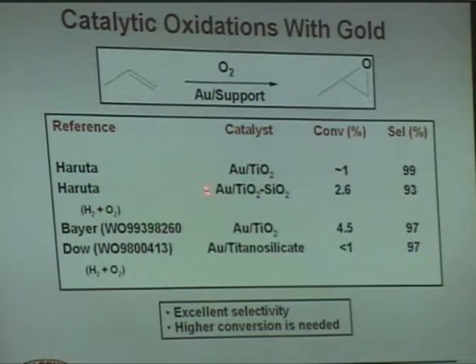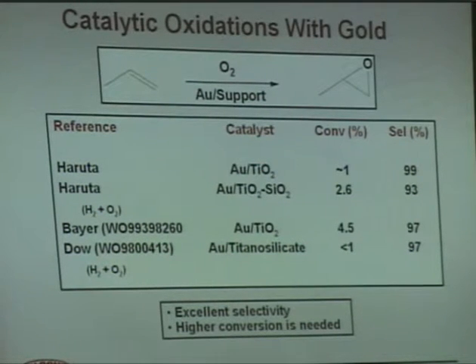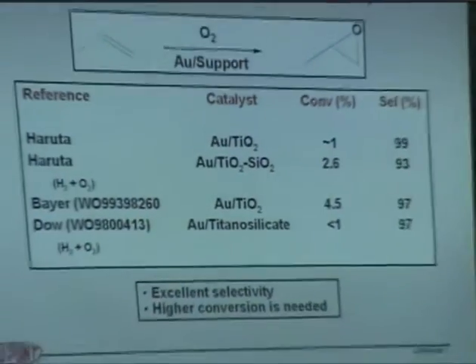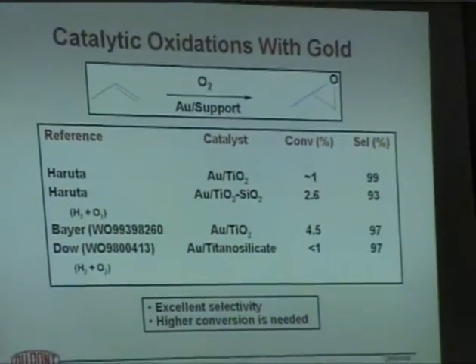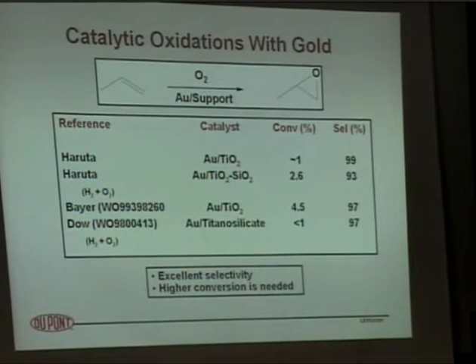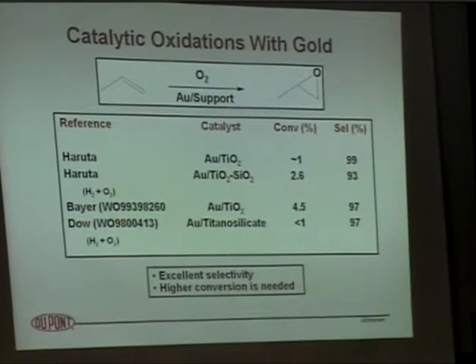There's still some real problems from a conversion standpoint, but using gold, the old coinage metal, inert metal, turns out to be a very nice active catalyst for the selective oxidation of propylene to propylene oxide. Selectivities of 95, 99%. Unfortunately, the conversions are still fairly low. 1 or 2%, as high as maybe 4 or 5% in the literature. You'll find some examples. So, I don't know whether this is going anywhere or not, but it's another example of finding different catalysts to get high selectivity and reduce CO2 emissions.